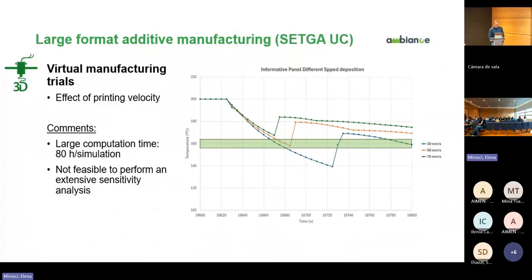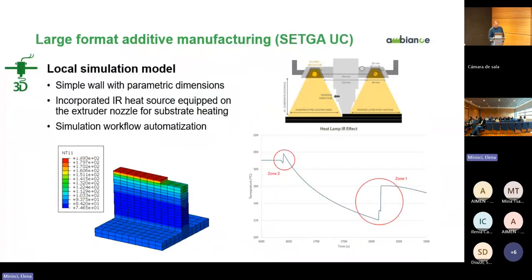The problem of this simulation, for example for this furniture part, the informative panel, is that they take long. Just to give an example, this simulation, as we have seen, took 80 hours to run in a server, just one combination. So in this case, it was not feasible to use this very heavy, very costly model to generate a DOE of simulations, because it would take much longer. So we take a different approach.